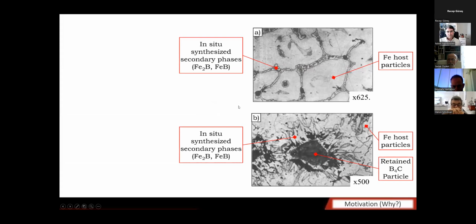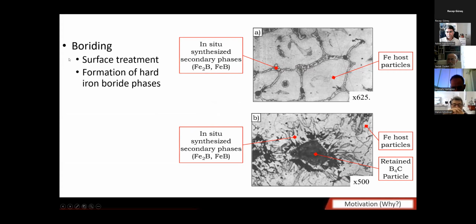Okay, this is totally related to my study because they have used iron boride phases, low iron boride and high iron boride phases, and they have used B4C particles for the strengthening of iron host particles. But before going to that, we need to understand what exactly is going on here. Boriding is a surface treatment which you all might have heard of, in which boron particles are impregnated. Actually, they are diffused into the iron lattice and surfaces of steel materials. Steel hosts are hardened, and they are used in wear applications, mostly wear and high oxidation applications, and they give corrosion resistance to the material. What happens is the formation of hard iron boride phases on the surface of the steels.